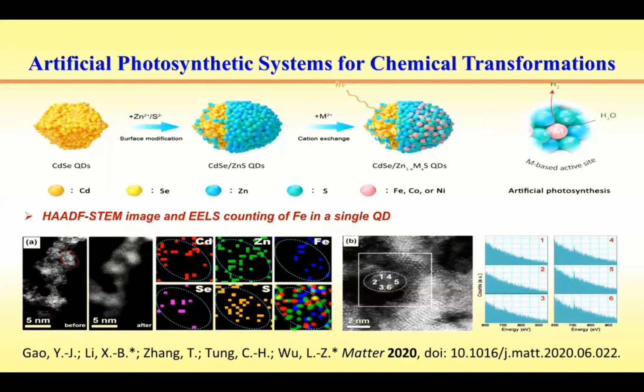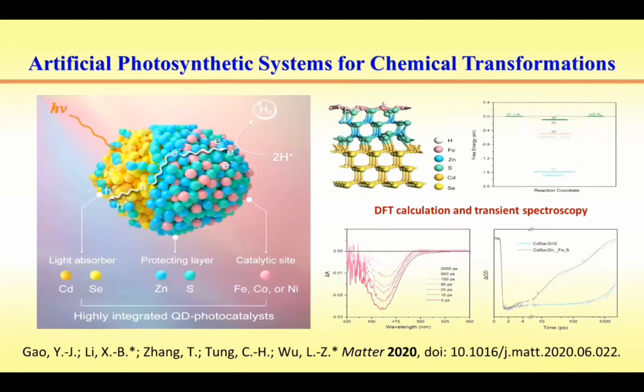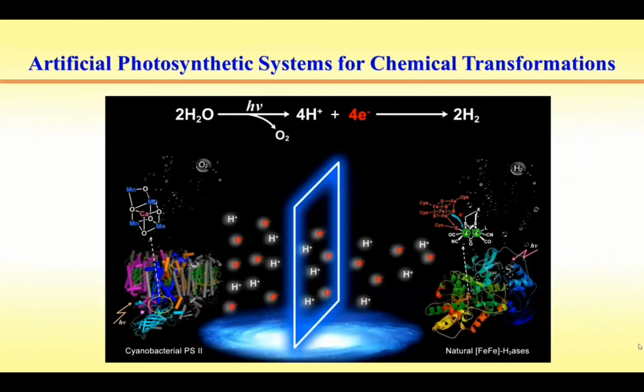By taking the anisotropic zinc sulfide shell as a medium to anchor the catalyst, the synthetic catalyst is able to capture sunlight and induce electrons to the active site, with the catalytic center at the active site for hydrogen generation. These strategies provide a route for preparing a multifunctional, ultra-small artificial photocatalyst for hydrogen evolution. By mimicking hydrogenase in nature, we have established artificial hydrogenase to reduce protons to hydrogen with remarkable activities and stabilities.